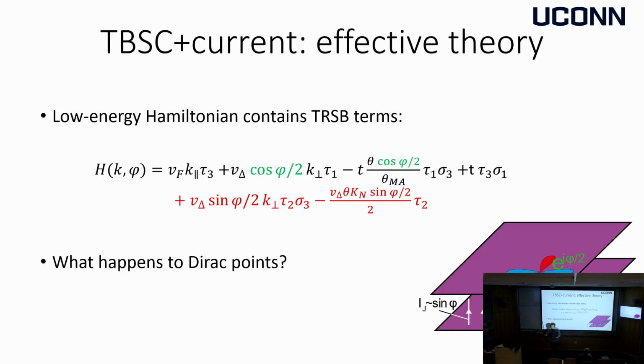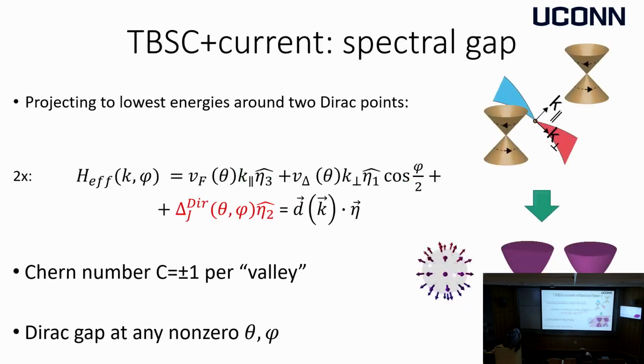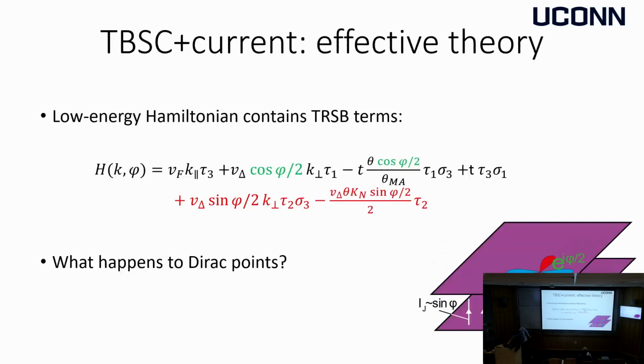So in some sense, we're by hand inducing this secondary order parameter, which is going to gap out the Dirac points. Indeed, this is what happens if you project these terms induced by the phase difference to the original Dirac points. They get gapped, and moreover, they get gapped with the same chirality for the two Dirac points. So if you calculate the total integrated Berry curvature over the two gapped Dirac cones, you're going to get 1 or -1. Notice that this gap opens at any non-zero twist angle and phase difference.